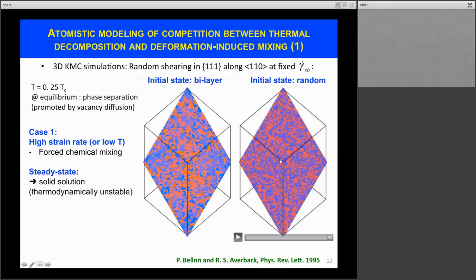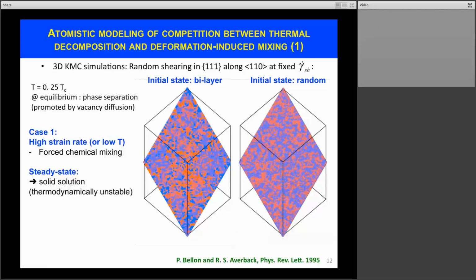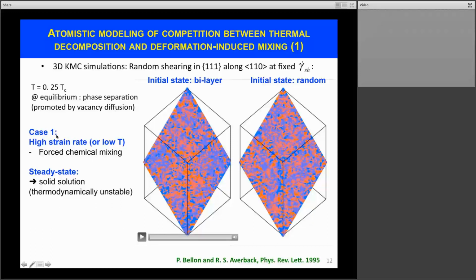If we had started with a random state, which is the movie on the right here, since we are imposing random shearing, we expect this random state to remain stable, and this is what you see again in that movie. And so here in this case, at high strain rate, or equivalently at low temperature, this two-phase system, or phase separating system, reaches a steady state, which is a solid solution. And it's remarkable already because this state thermally would be unstable, and yet it is the stable, steady state of the system when it's subjected to high strain rate deformation.